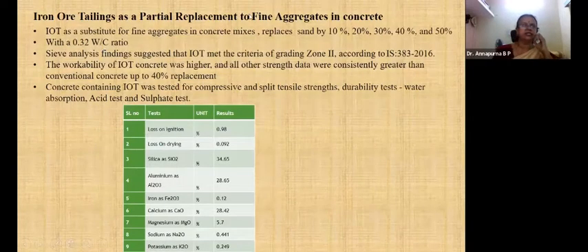Now this is iron ore tailings as a partial replacement of fine aggregates in concrete. This is work done by one of our researchers, so I have not mentioned the name here. So much research is going on in the department. Here the concrete mixes have sand replaced by 10, 20, 30, 40, 50%, retaining a water cement ratio of 0.32 to achieve high strength concrete. Sieve analysis was done, and workability of concrete was higher. All of the data were greater than conventional concrete up to 40%. Concrete containing IOT was tested. This is the test report of the IOT used for the test.